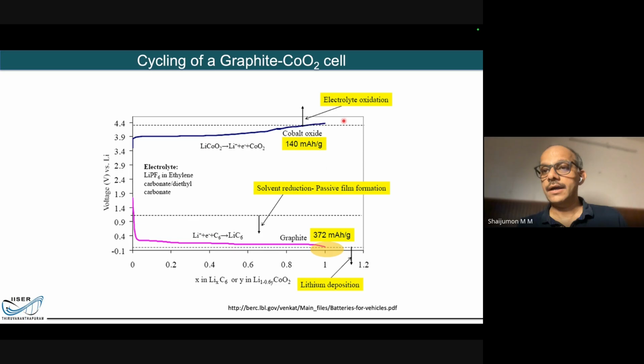So it's very simple, because as I said, at any point of time, the voltage difference between these two curves gives you the voltage of the cell. So if I wanted to increase my voltage so that my energy density can be improved, very simple, why not make some materials which will give me a higher voltage than this? Or why not think about some anodes which give me a voltage lower than this, below this, so that my voltage window is expanded? Sounds very simple, but then there are issues, and that is marked here by these yellow patches, right?